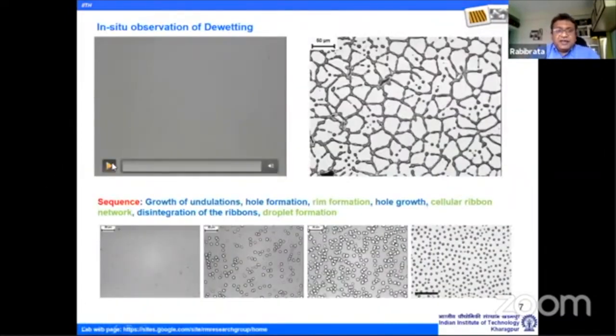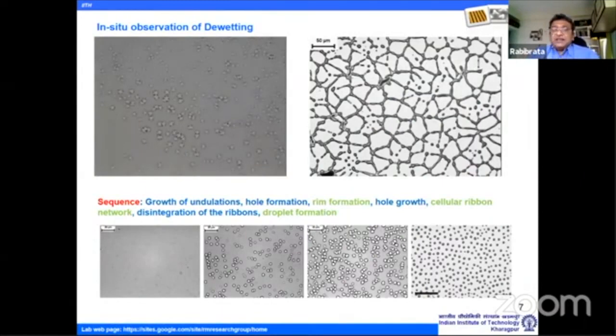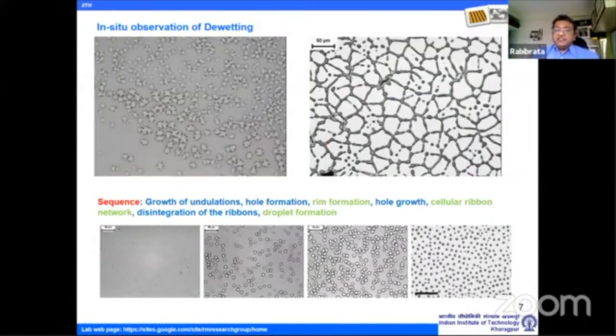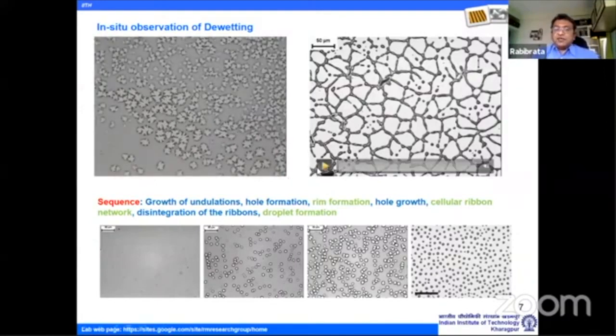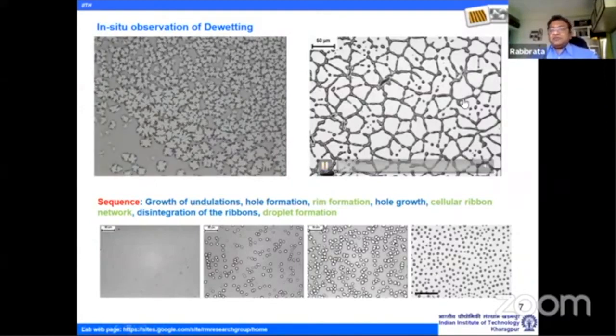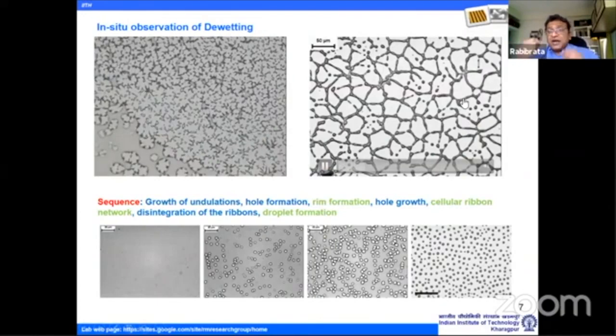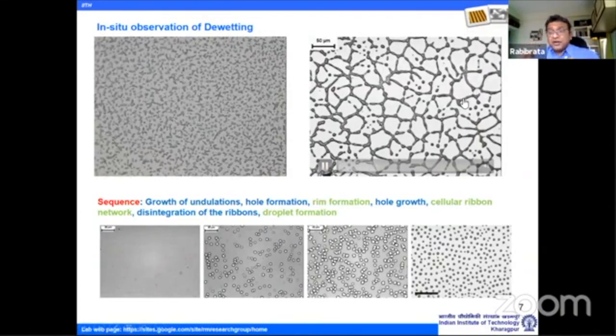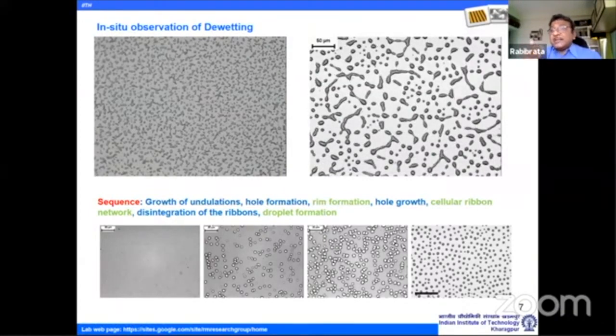What you will see is actually a polystyrene film heated above its glass transition temperature to take it to a liquid state. And all you do is do nothing. And you see that the film has disintegrated into these holes, and these holes evolve and it forms some droplets. So I was asking how thin a coating you should go for. These are the restrictions. That is the reason you cannot go for very, very thin coatings, right? So you end up taking coatings which are slightly thicker.